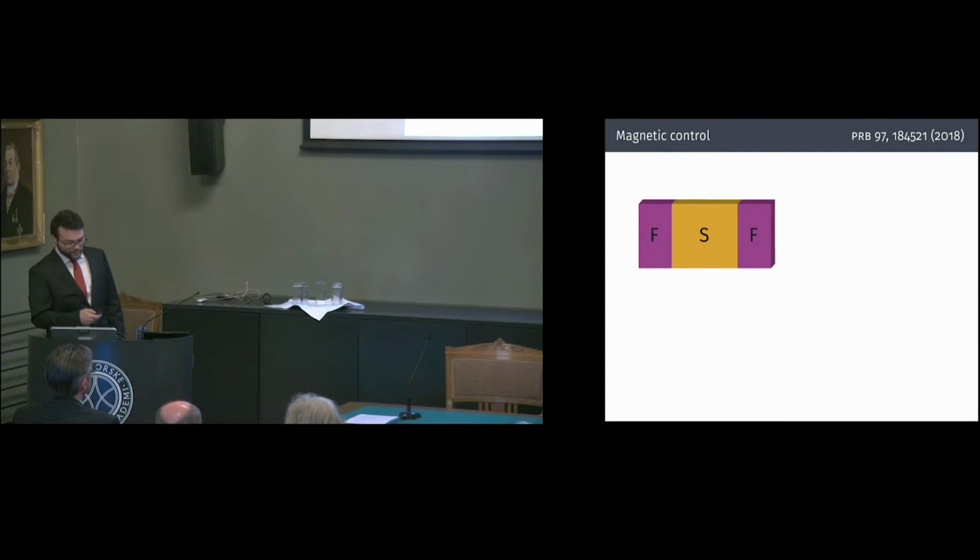And so first, just to give a brief background. If you take a superconductor and you place it between 2 ferromagnets, in this case the superconductor is supposed to be really thin, like 30 nanometers or something, then the ferromagnets might end up just killing all the superconducting properties entirely. So then the system looks more like this. The N here stands for non-superconducting or normal.